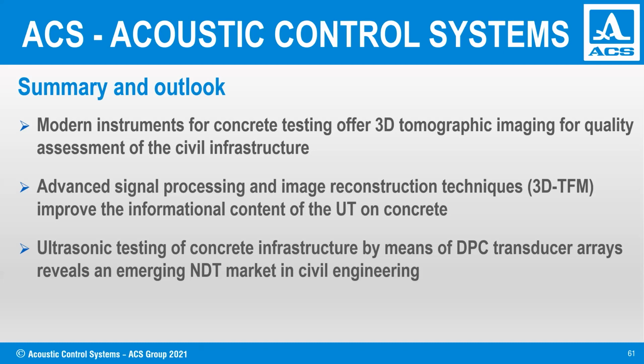Okay, first of all, obviously the physical principle: in the georadar, electromagnetic waves penetrate the material and are used to visualize the inner structure. In ultrasonic, these are ultrasonic waves, which are mechanical waves. But that is not the point. The thing is, ultrasonic waves can penetrate a little bit better in the material. For example, if you have humidity or too many rebars, electromagnetic waves cannot penetrate because they are shielded. They are attenuated too much by this material. For that reason, UT can penetrate deeper.